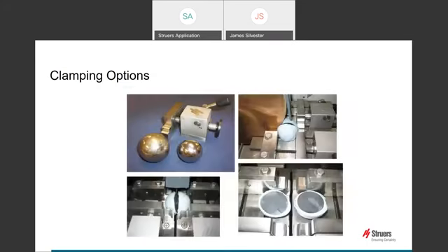This challenge of cutting a spherical ball which contained cemented carbide required an out-of-the-box thinking solution. The solution used actually makes the cut quite simple to complete in the end. Due to the shape, it is difficult to fixate or clamp during cutting with almost any clamp available. In addition, the hardness of the material made it very difficult to clamp and hold in position during and after the cut. The solution we found was to mount the ball in Replifix before cutting. This made it possible to clamp and cut more easily with a standard quick clamping tool. The Replifix was easy to remove after the cut to retrieve the sample.